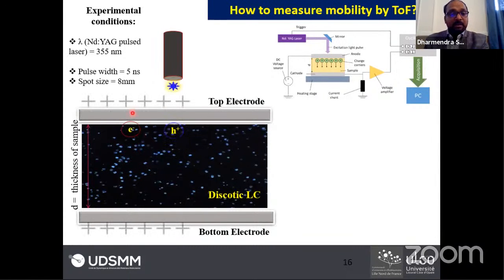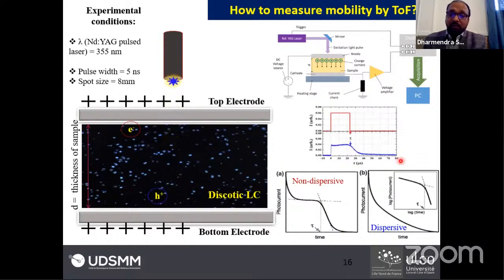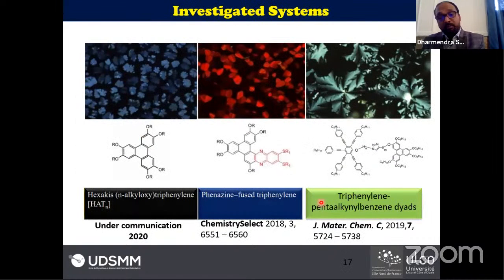Later on, when we apply a positive field between the top and bottom electrodes, holes propagate from the top electrode to the bottom electrode. So this technique is really fantastic to measure separately the hole mobility and electron mobility, and if your sample contains ions, you can also estimate the ionic mobility. If you apply a negative potential here, then electrons will move from here, and you can estimate the electron mobility. In general, we obtain two types of transient photocurrent curves, that is non-dispersive and dispersive. By measuring the transit time, we can calculate the mobility of the material.